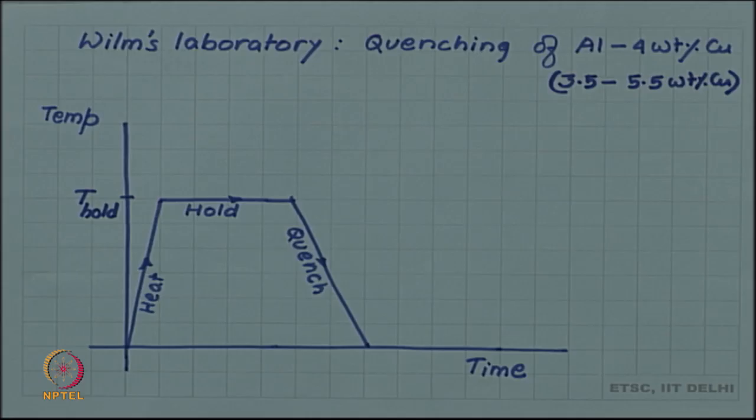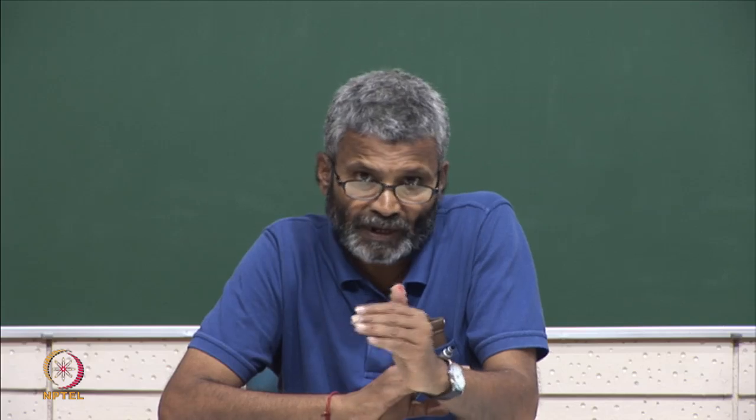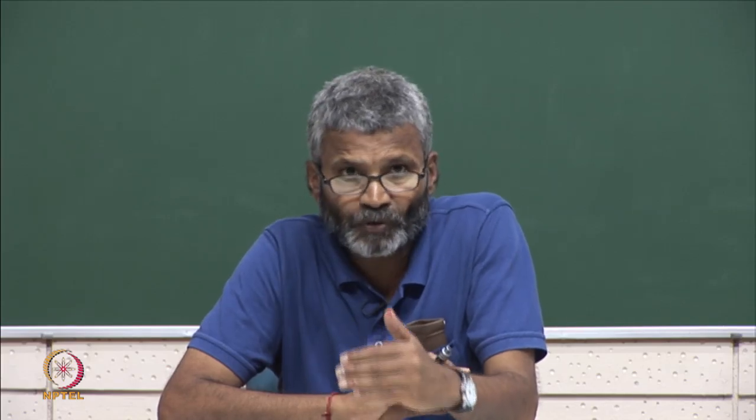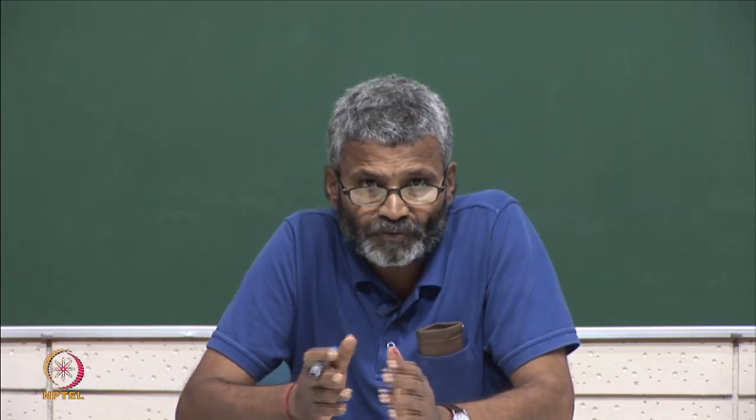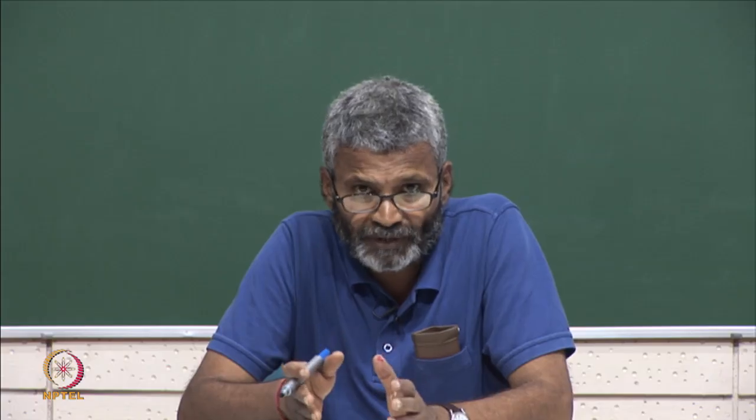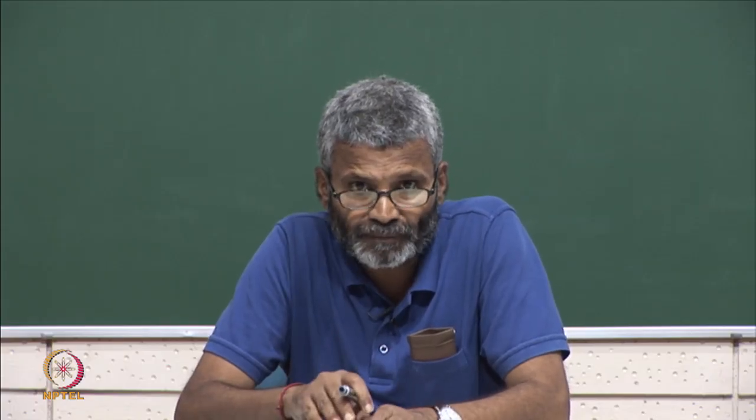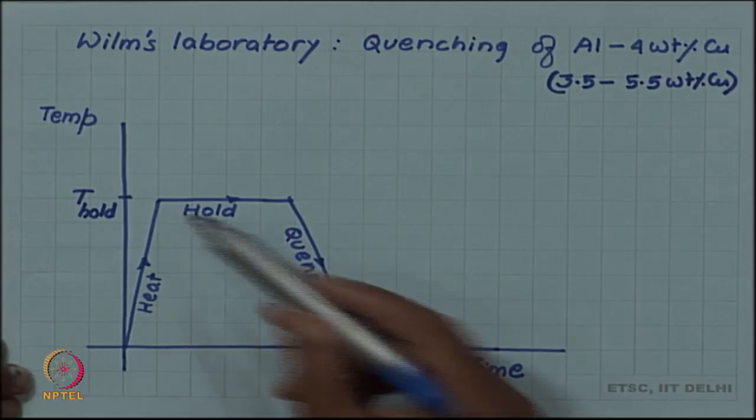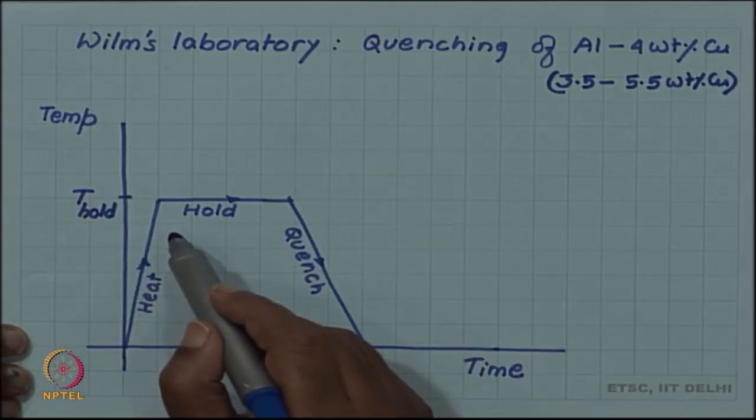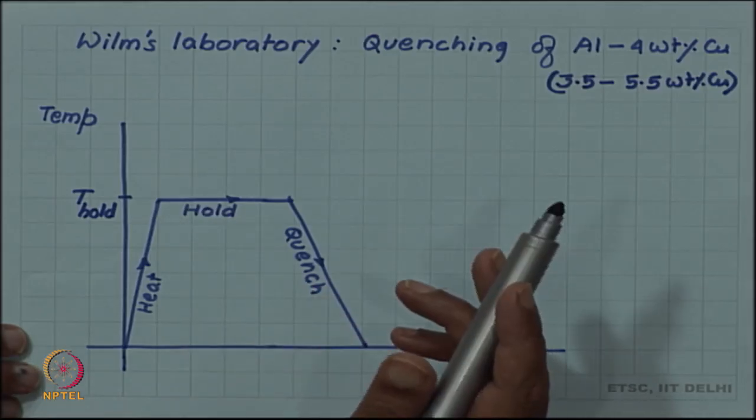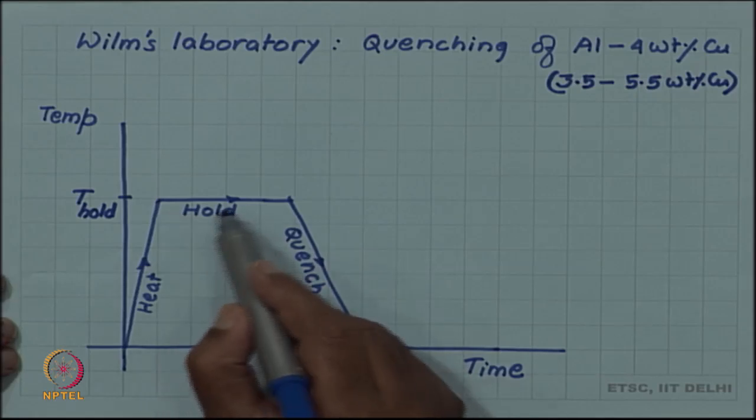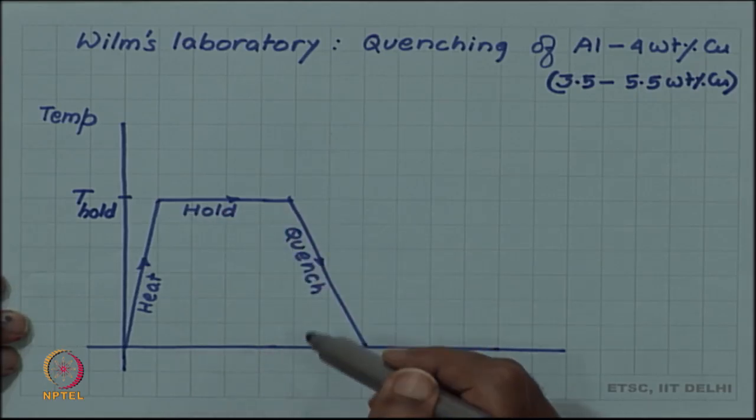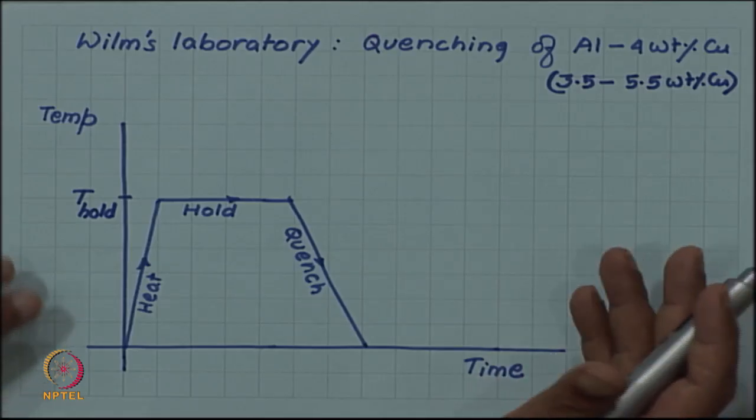We know from the steel example that if we do not go to the austenite temperature range in which austenite phase is stable then and quench it below the eutectoid, it is not going to have an effect. You will not have austenite to begin with and there will be no martensite forming. Thus if you want to form martensite you have to heat it above austenite temperature. Is this hold temperature important? He varied the hold temperature. Similarly, in austenite you find that unless and until austenite is quenched rapidly enough to miss the nose of the TTT curve martensite will not be produced.